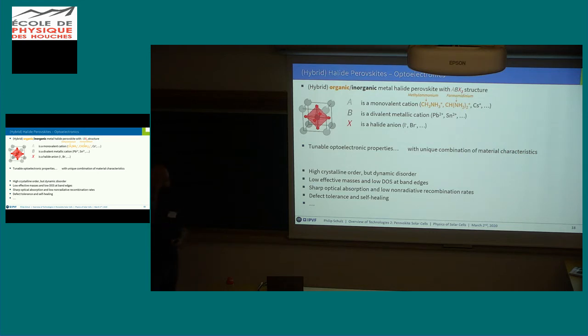recombination through defects, but it also poses a problem for one of my favorite characterization techniques, which I will explain tomorrow, because it's very hard to capture these sharp edges. You have sharp optical transitions and low non-radiative recombination rates. And then a last point here that I want to raise: defect tolerance and self-healing.